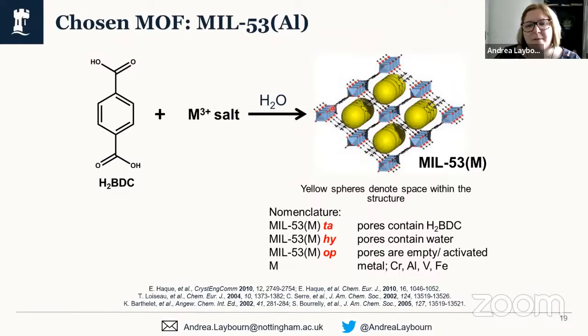In this case, you've got the aluminium oxygen secondary building unit. The linker bridges between those secondary building units, and then you've got the void space shown by these spheres. This MOF, when synthesized, can produce different phases. There is the terephthalic acid phase, where the terephthalic acid is intercalated into the pores during synthesis. You can get the hydrated phase because we are working with water as our solvent, so you can get water present within the structure. And then you can get the open phase as well, which is the material where there is nothing within the pores.